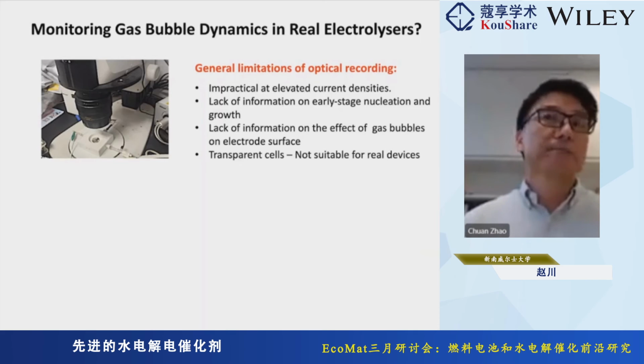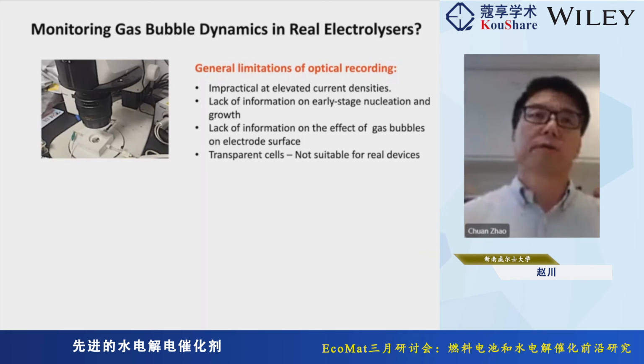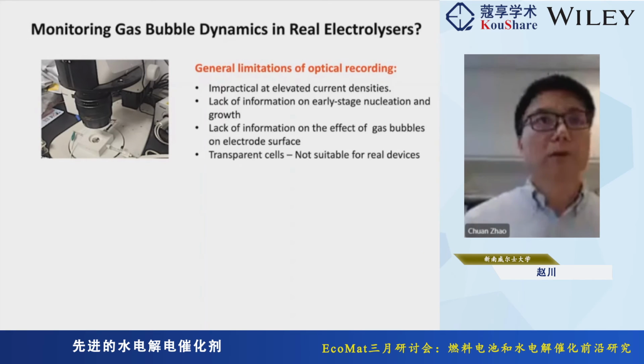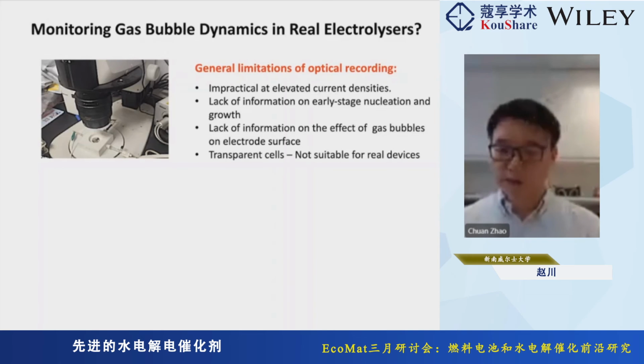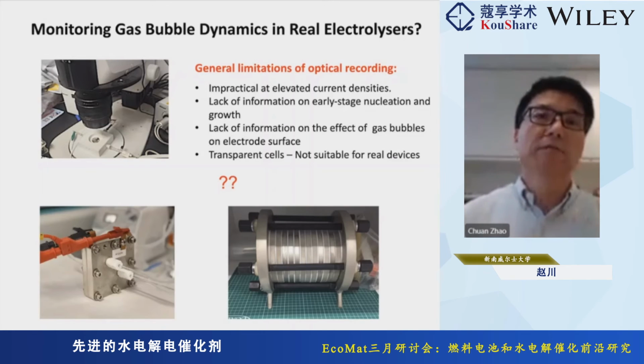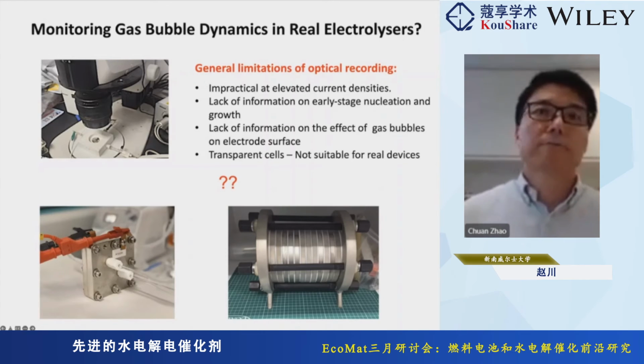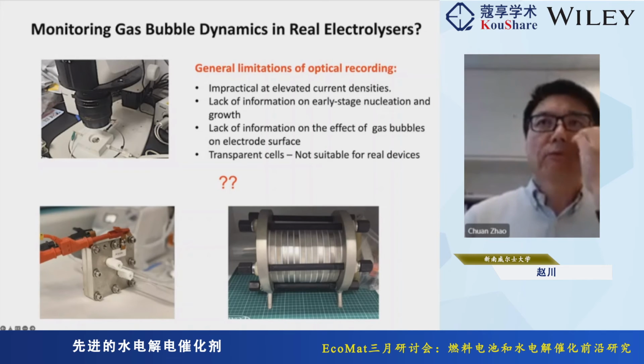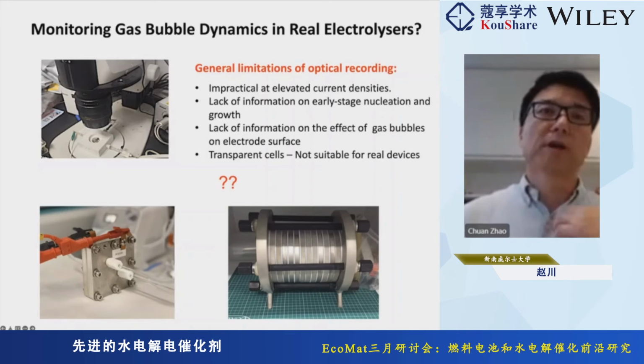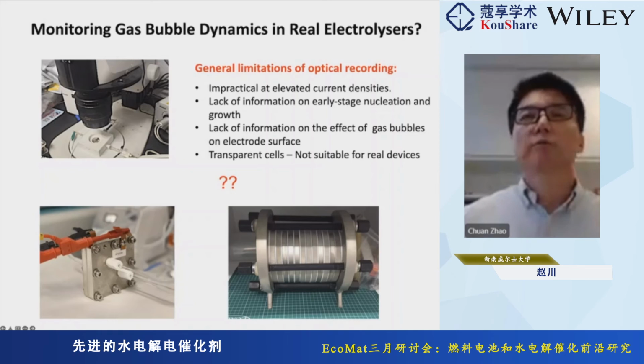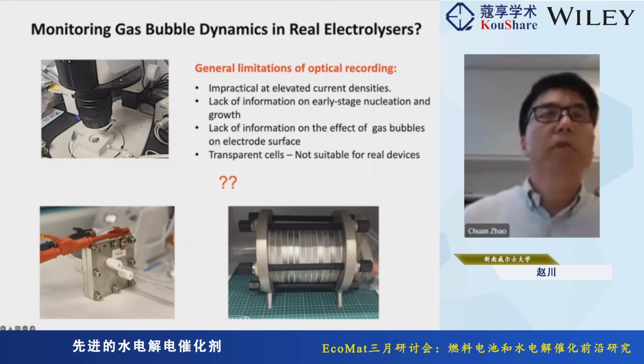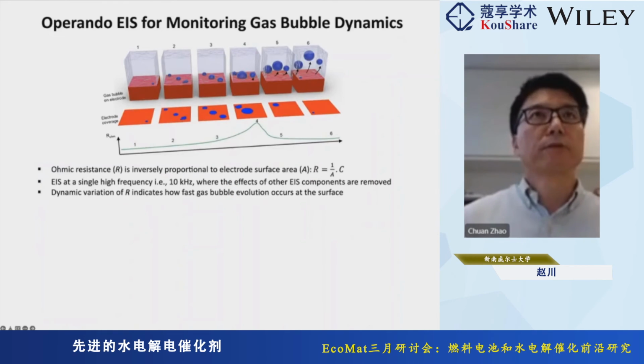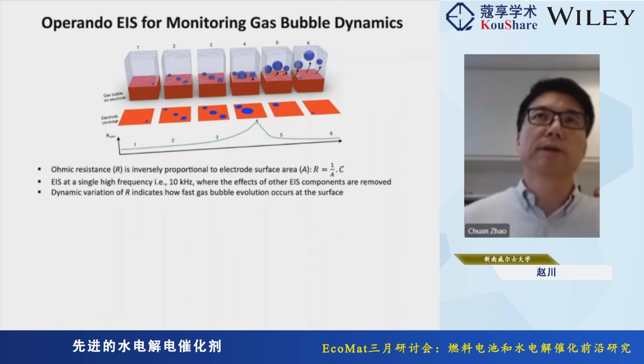And also, when you see a gas bubble, you don't know whether it's attached to the electrode surface and affecting your current or not. But more importantly, optical imaging requires the cell to be transparent, but in reality, the cell is made of metal. So we need other approaches, or complementary methods, to monitor the gas bubble behavior. So we've introduced this operando electrochemical impedance spectroscopy method to monitor the gas bubble dynamics.